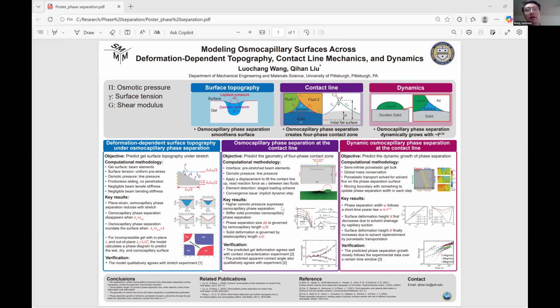We find that higher osmotic pressure suppresses phase separation, and a stiffer gel promotes phase separation. The phase separation size and the solid deformation scale are governed by an osmocapillary length and an elastocapillary length, respectively. Our result agrees well with the experiment data from the other literature. In part three, we predict the dynamic growth of the phase separation.